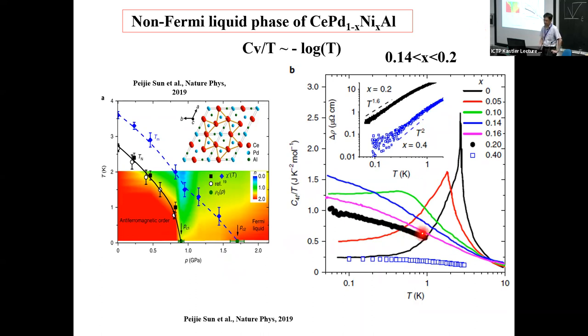Here is the same thing. So if you make a fit to this figure, you can see that there are two kinds of logarithmic divergence, which I will address in just a moment. So first, at intermediate temperature range, you could fit this data by a logarithmic curve, and at the very low temperature, close to the ground state, you could also fit this by another logarithmic divergent curve. Okay, so double logarithmic curves are seen here.